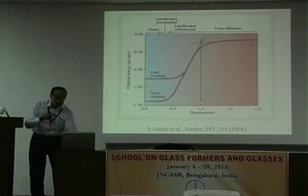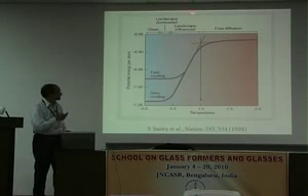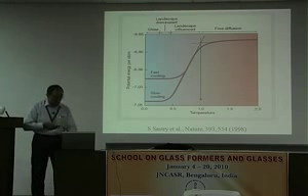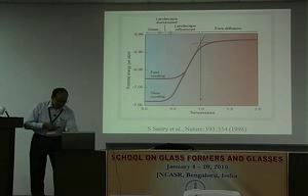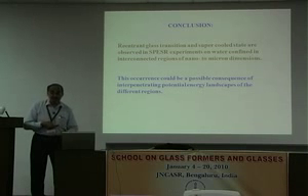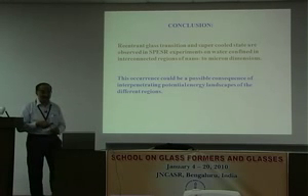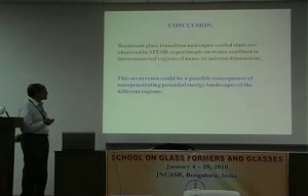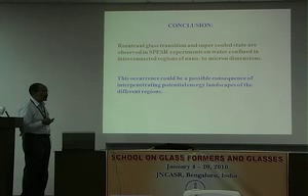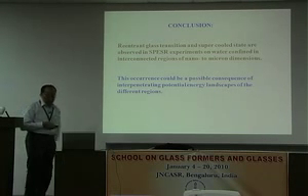This is a classic paper of Professor Sastry, where there is a region identified as landscape influenced region, but I stop here as promised, not taking too much of your time before lunch. And the main conclusion is that reentrant glass transition and supercooled state are observed in spin probe ESR experiments on water confined in interconnected regions of nano to micro dimensions, and this occurrence could be a possible consequence of interpenetrating potential energy landscapes of different regions. Thank you.